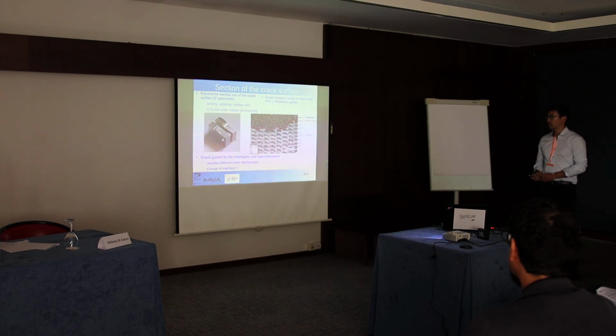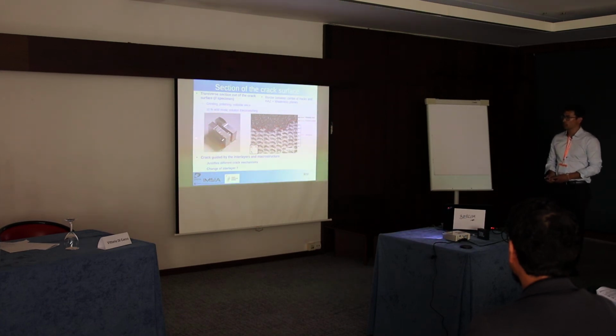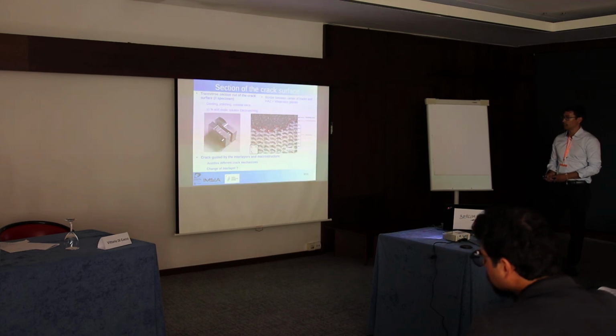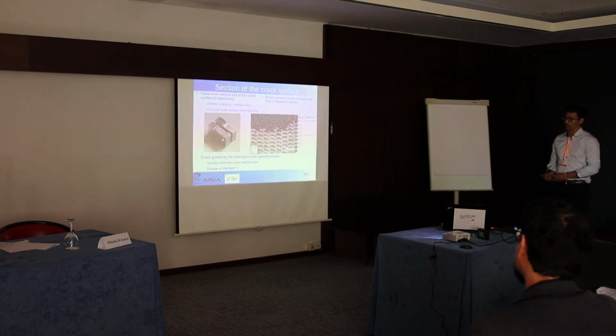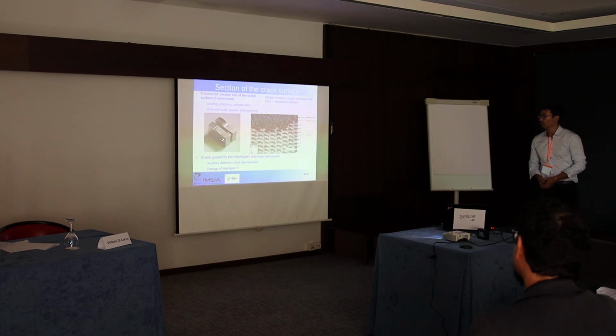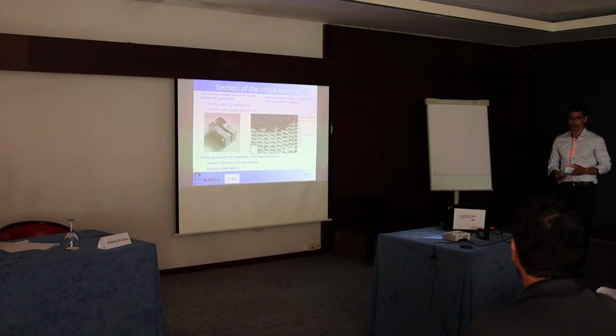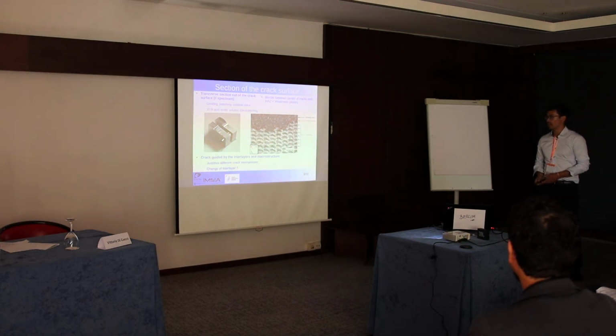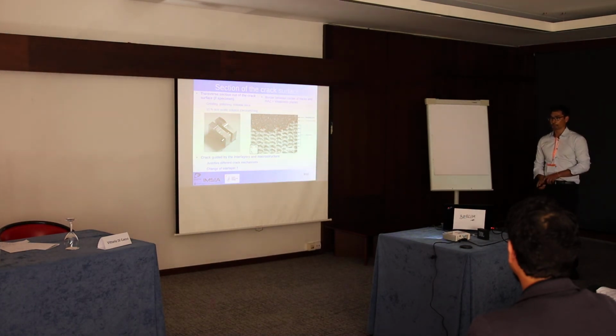So here we have the interlayers between the different tracks, and this illustrates quite nicely that the crack actually goes from interlayer to interlayer, and the tortuous aspect that was observed earlier is actually caused by the switching of the crack from an interlayer to the neighboring one. This appears to justify the differences observed in the two cases. So we have seen that the interlayers act as weak planes for the crack growth.